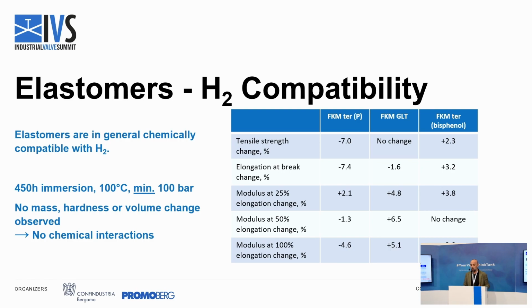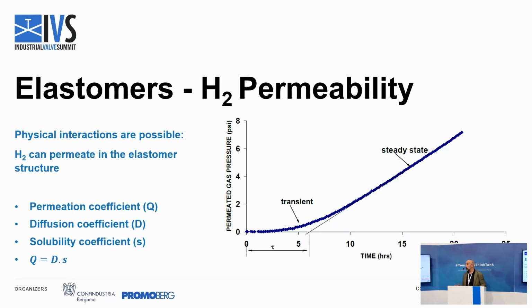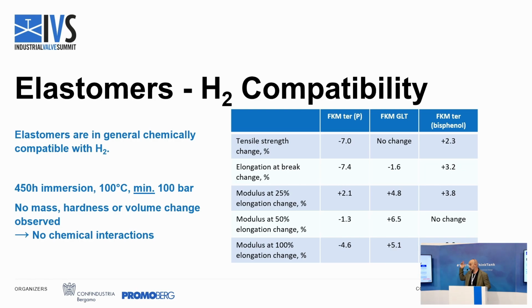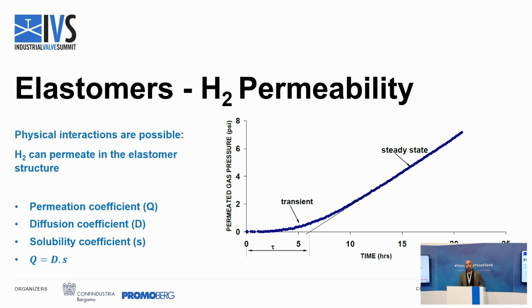Hence, we need to also control and check the permeability of this gas in the elastomer. If we run this same test with helium, the results will be more or less the same. No chemical interaction, no aging, etc. But we know that elastomers are not permeable to helium, at least not as permeable as to hydrogen. Hydrogen, we saw, has high permeability in the elastomers and also in other materials.